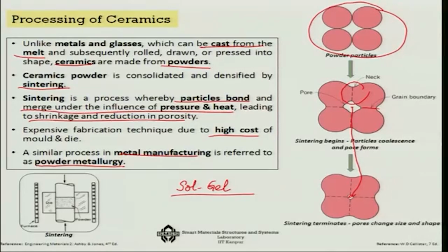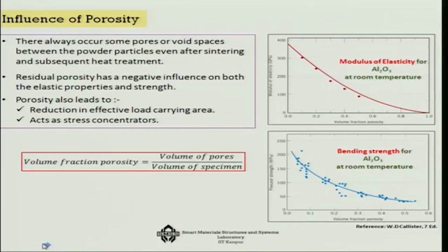Okay, so this is how ceramics are processed, and we are showing here that in the process of making ceramics, pores are inevitable. So, what is the influence of the porosity? Because there will always be some pores or void spaces between the powder particles even after sintering and subsequent heat treatment. Pores are unavoidable. The porosity has a negative impact on the elastic properties and strength. For example, you can see here that the modulus of elasticity of Al2O3 at room temperature continuously comes down as the porosity increases. Similarly, as the volume fraction of porosity increases, the strength comes down.